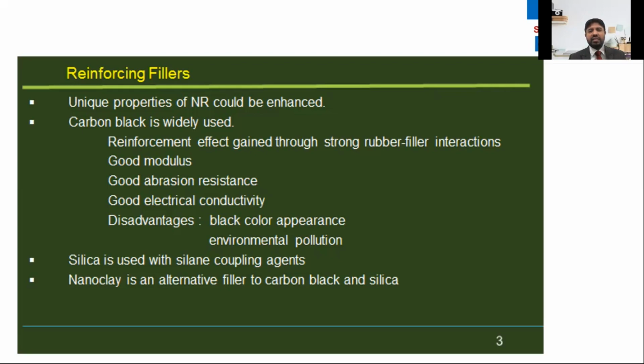I would like to discuss other types of filler before I come to the topic of nano. Carbon black is widely used as a filler with natural rubber. We can obtain a better reinforcement effect from it because carbon black forms strong rubber-filler interactions with natural rubber. It gives good modulus, abrasion resistance, and good electrical conductivity. But there are some drawbacks of carbon black. We cannot apply carbon black for producing colored products because of its black color. It also causes environmental pollution. So one of the best solutions for this is silica used with a coupling agent.